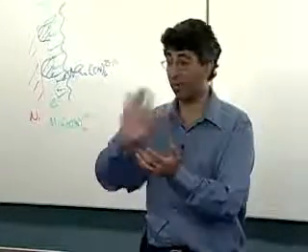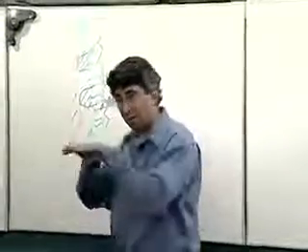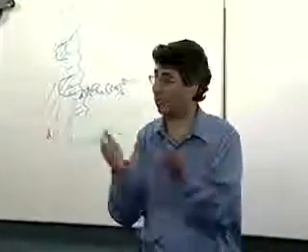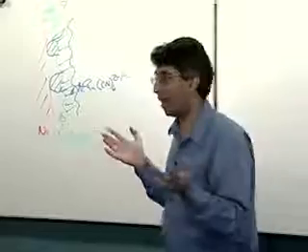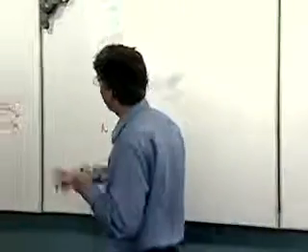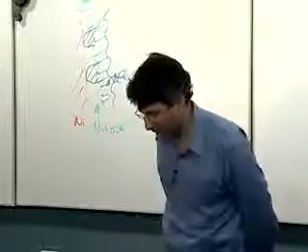Then we did another experiment where we took a ring disc electrode and derivatized the nickel disc with this material. The ring is set at a potential where it will detect the ruthenium cyanide if it comes off the disc, and we rotate it and simply ask, can we detect any ruthenium cyanide this way? And the answer is no again. So we're now convinced that if there is some ruthenium coming off, it's not enough to do this catalysis at the rate we are observing. So we still have the problem of how to get an electron from here to here, because everybody says an electron travels maybe 10 angstroms, something like that.